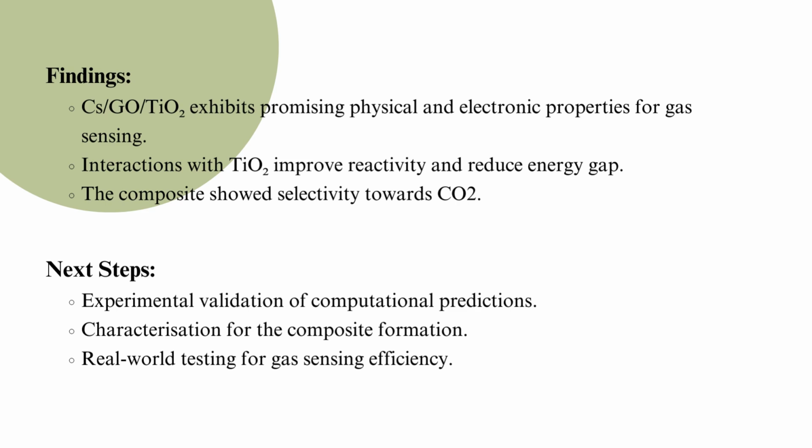Notably, the composite material exhibits a distinct selectivity towards carbon dioxide, likely attributed to a combination of factors, including specific interactions between CO2 molecules and the surface functional groups of GO. Future work includes experimental validation and further characterization; the sensing experiment is yet to come.